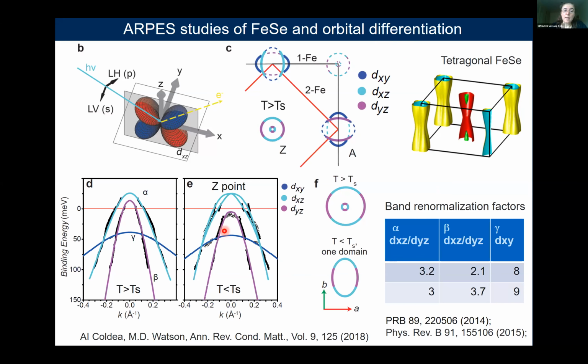As we enter the nematic state, the effects we see are quite striking. We can see that these two bands, it's almost like they repel each other. One of them shifts up and the other one shifts down. And these are the effects to do with orbital effects, band shifts associated with the transition into the nematic phase. And while these band shifts occur, then the Fermi surface changes from an isotropic circular Fermi surface to a very elongated elliptical Fermi surface. And the small little pocket which was present at the Z point disappears completely at low